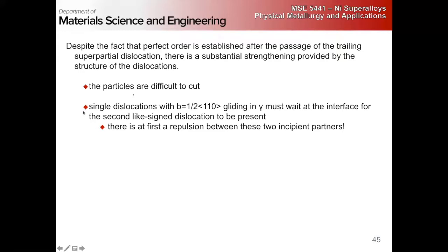We talked about some of the reasons why the particles are difficult to cut. A single dislocation is going to come in, and by entering the gamma prime phase, it increases the energy quite a lot. So if we had perfect 1/2<110>s, which we don't, we have Shockley partials, but just imagine that we do, the first one is basically just going to hang out there at the interface. It's not going to cut in because the energy cost to create an APB is too high. So it's going to wait till a second dislocation of the same sign comes up. But they're the same sign, so they repel. So you have to bring them close enough together for them to cut, so that the width of your APB interface is small.